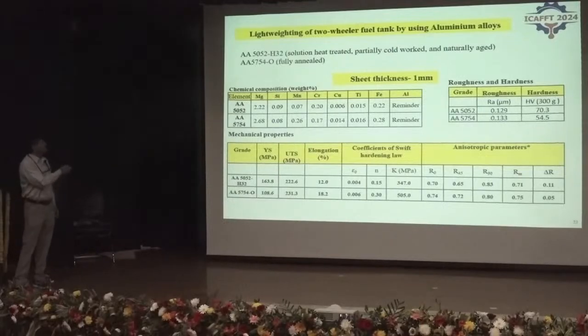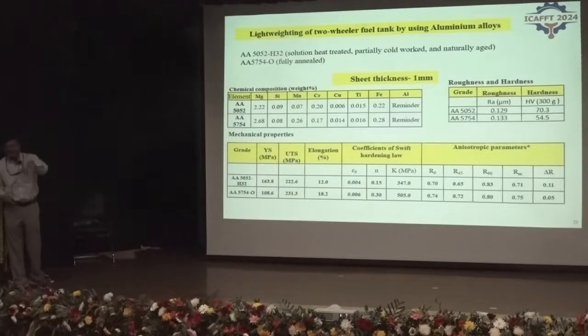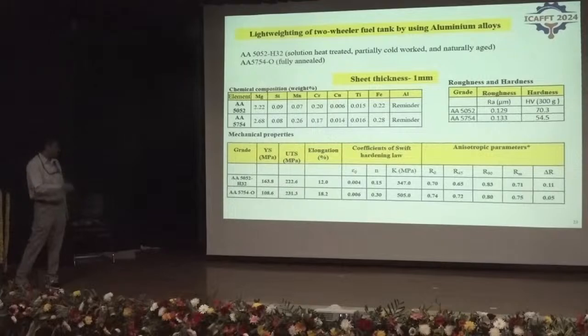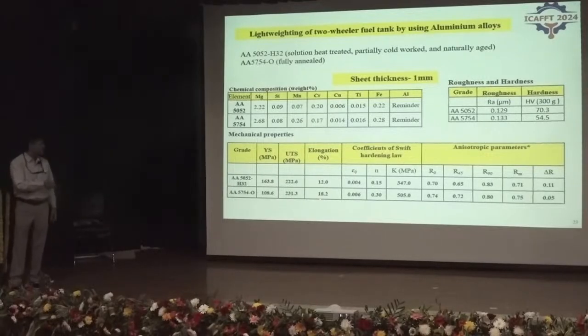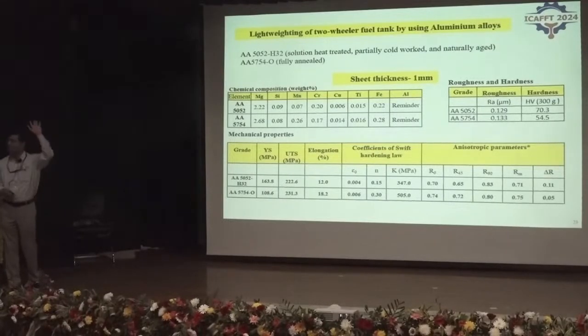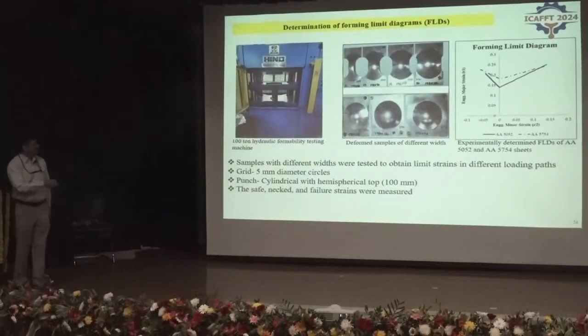And the second one is 5754. Since it has enough strength and formability in the annealed condition, we used it in the annealed condition. So you can clearly see that 5754 has much better strain hardening ability, even though the drawability of both the materials is much inferior when compared to steels. So we started the simulations with 1 mm, and this is the determination of forming limit curves for both the materials experimentally, and these forming limit curves have been used as the failure criterion in the simulations.